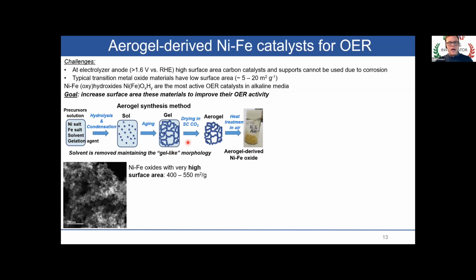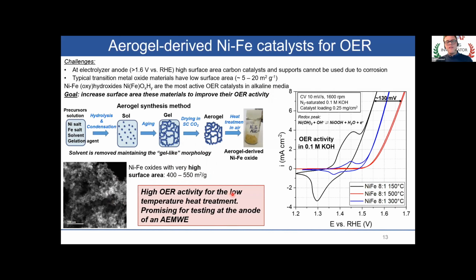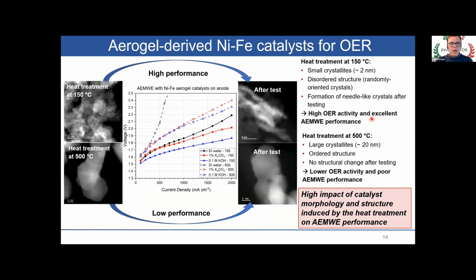This method is based on aerogel synthesis. So the aerogel method basically enables us to remove the solvent and create a gel-like morphology in a solid material. So we obtain a very high surface area nickel iron oxide with more than 400 square meters per gram surface area, which, when undergoing different heat treatments at different temperatures, showed that heat treating at a low temperature like 150 degrees C shows the best oxygen evolution reaction activity.